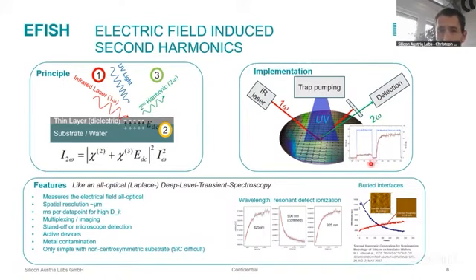And here you can see an example measurement. The first block in the measurement, you see the red curve, nothing happens, just some basic offset. The infrared light was weak here, so there's no multiphoton ionization. And then we turn on the UV light, and the traps in the interface layer get quickly populated. After you populated the traps, you can measure on the plateau, and the measurement on the plateau is fairly quick. So you get a data point in a millisecond or something. So in terms of throughput, it's sensible to speak about in situ implementation for this. You can measure rather fast once you have populated the traps.